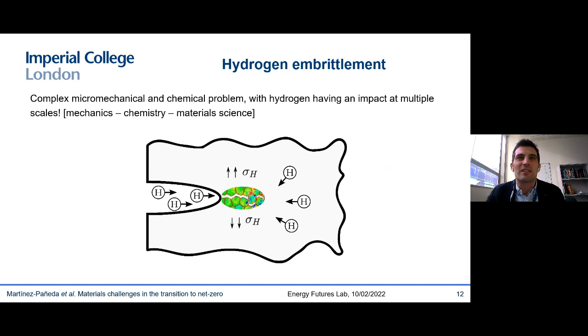But then what hydrogen does here in this fracture process zone is complicated, and it really interacts with the material in many ways and at multiple scales. It can change the dislocation mobility, it can stabilize vacancies, it can reduce the bonding strength between metal atoms. So the physical picture is complicated. And this is one of the reasons why we're being precluded from predicting those failures.